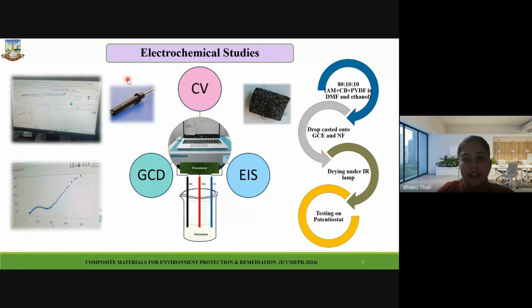Further, we have done the electrochemical studies using a 3-electrode system and a potentiostat on two substrates. The two substrates which we had chosen were glassy carbon and nickel foam to assess the comparative electrochemical performance. Our electrodes were prepared using the active material, carbon black, and PVDF dispersed in DMF and ethanol. Further, they were drop casted onto glassy carbon and nickel foam.